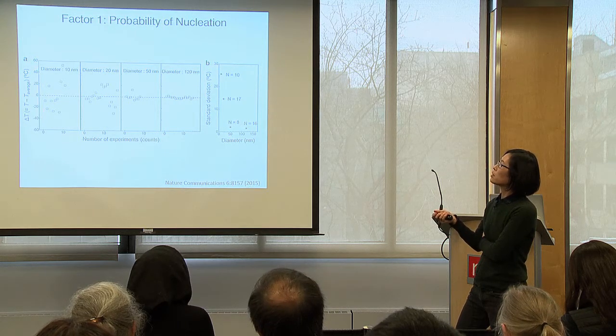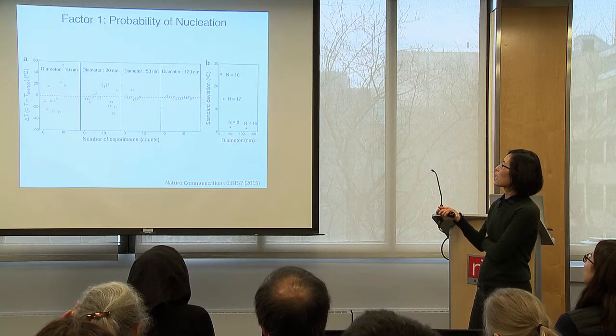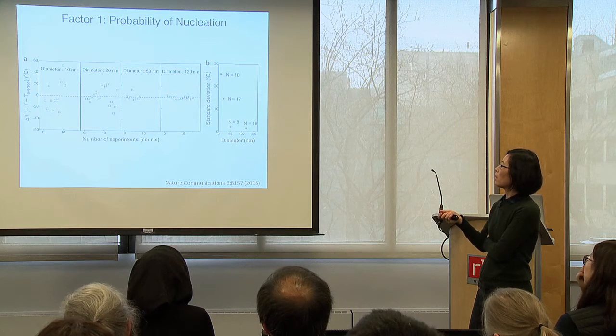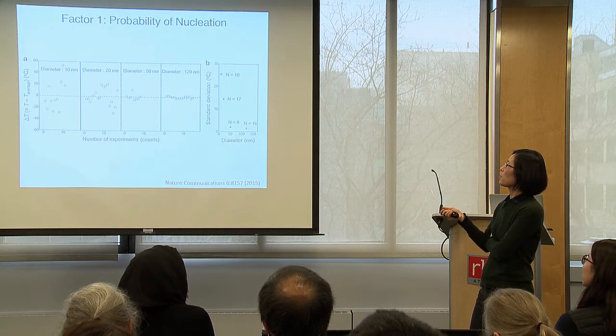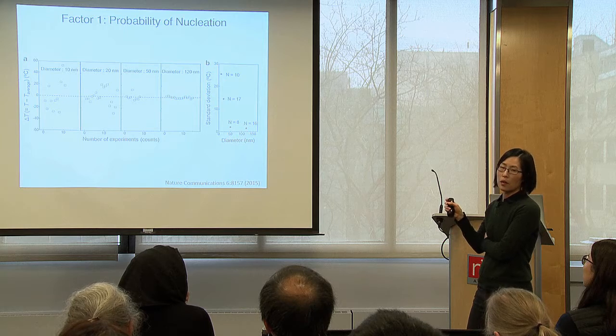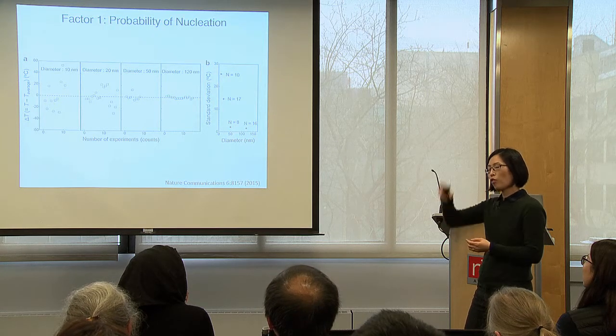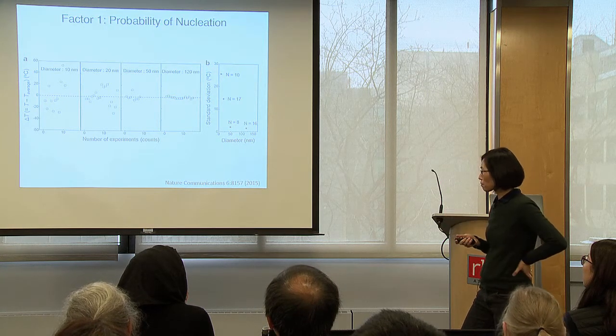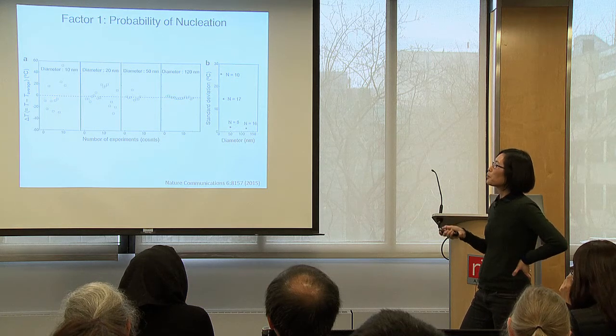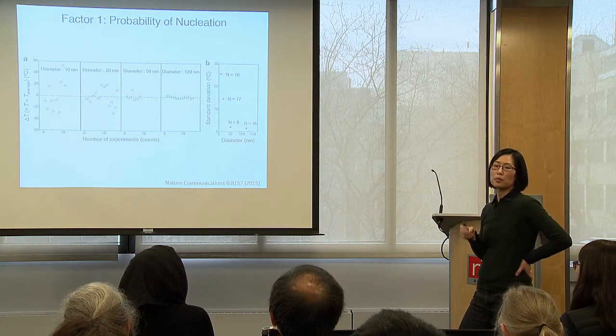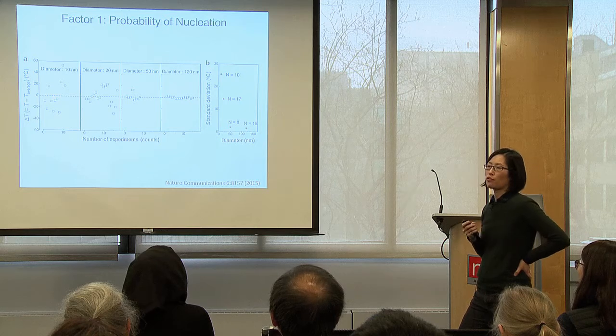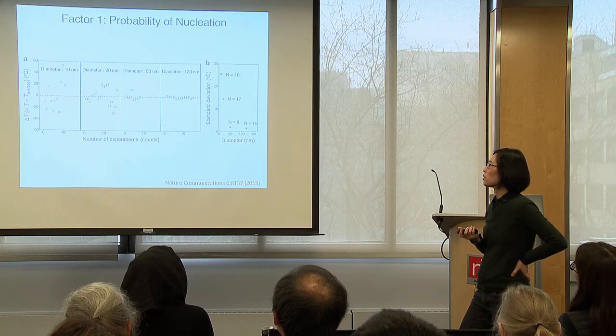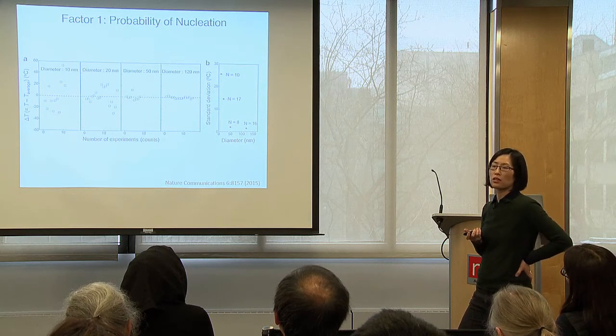So for smaller rods, we have more scatter. If you look at the standard deviation of the scatter in the crystallization temperature as a function of diameter, we see that it increases. It's still smaller than the overall trend that we see, which is nice. So we think that the upturn of the crystallization temperature for very small rods is simply that we don't have nuclei in the sample. Okay? And that fits with the classical nucleation theories.